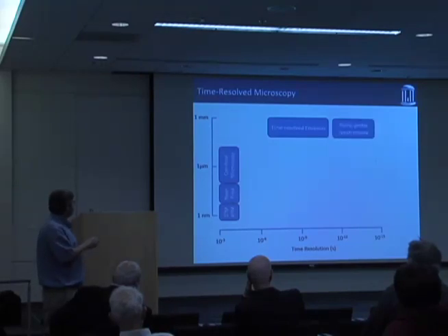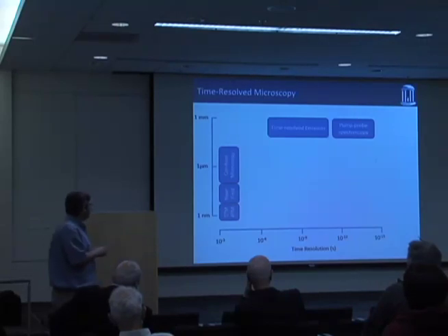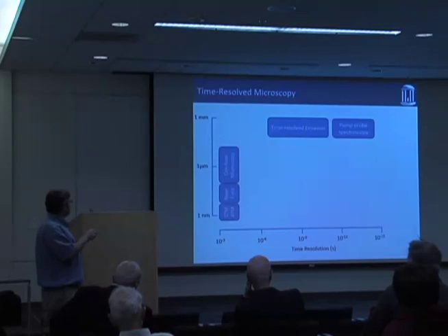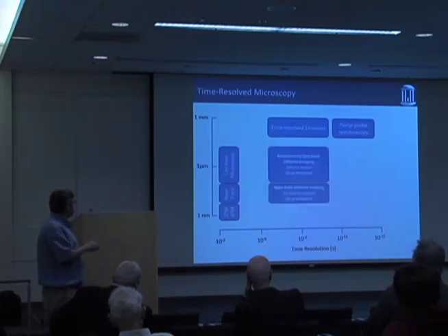And if you really want fast time response, you could do pump probe, and that's kind of the gold standard of sort of ultrafast spectroscopy. It gives you the highest time resolution, where it's determined by the laser pulse. But again, you have no spatial resolution. So the place you really want to be is in this part of the diagram.